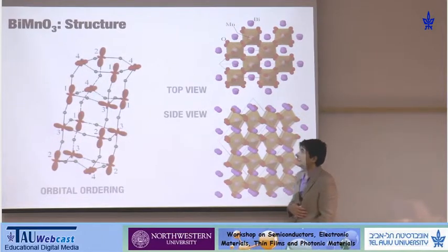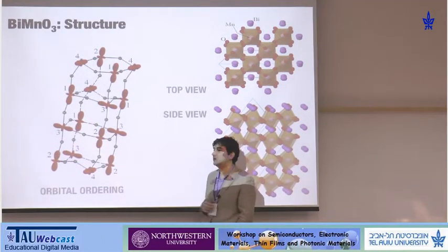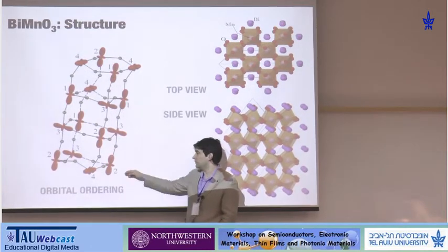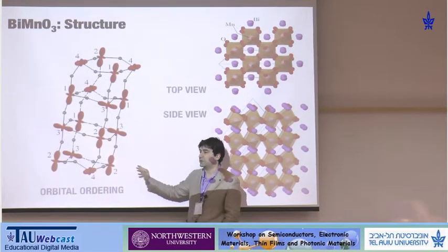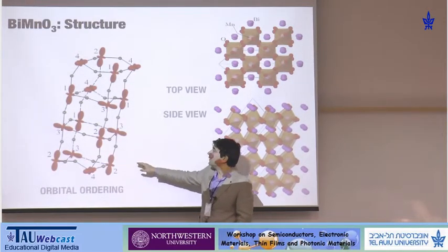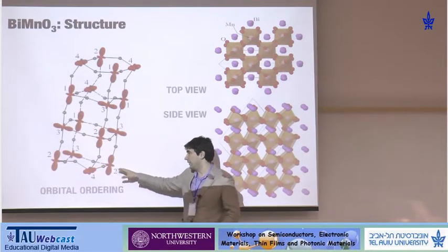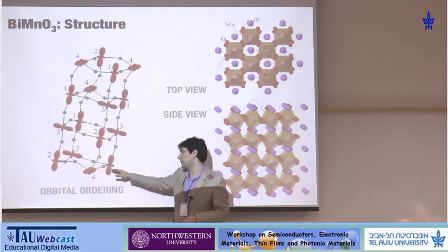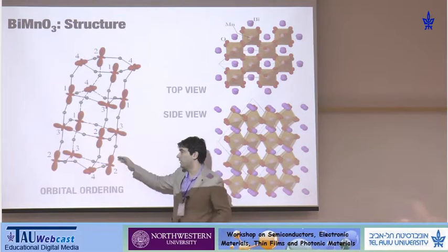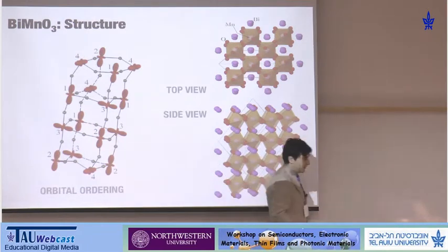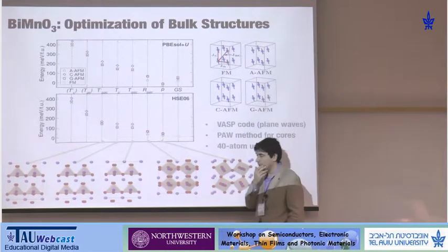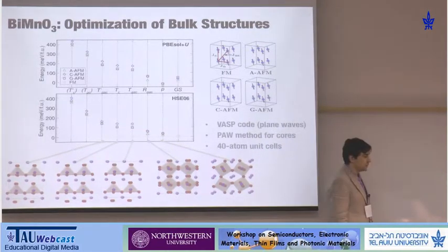We want, ideally, to keep the ferromagnetism and to develop polarization. First principles calculations were done before we did this, but they didn't find any transition in the material. If you try to grow it as a film and change the strain of the film, nothing happens. The phase is the same until at some point the magnetic moment disappears. The magnetism disappears.